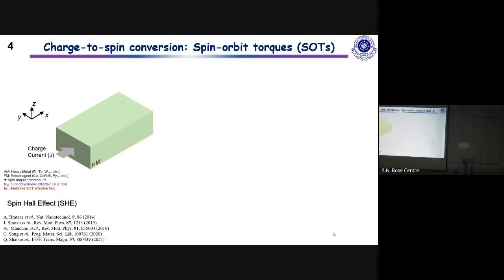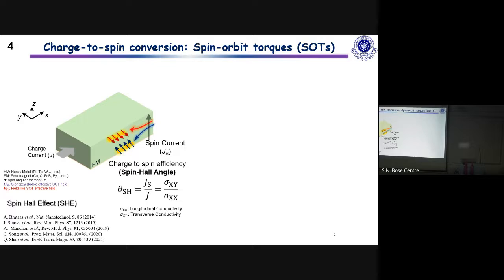Okay. So let me first begin by giving you a brief idea of what I mean by this charge to spin conversion. Very simply speaking, if you take a heavy metal with a strong spin-orbit coupling, for instance platinum, tantalum, tungsten, etc., and you pass a charge current, then that charge current would give rise to a transverse accumulation of angular momentum across all the four different faces of the cube. Here I have just shown two of them, but all the four faces will have spin accumulation with different spin angular momentum. And then you see that there is a transverse flow of spin angular momentum, which is called the spin current, and this ratio of the spin current to the charge current is called the spin Hall angle, which is basically the efficiency with which you convert the charge to spin.